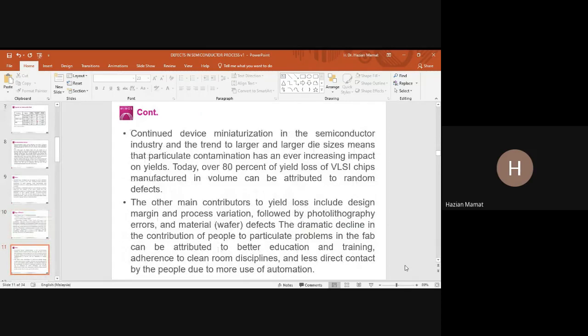Okay. Continued device miniaturization in the semiconductor industry and the trend toward larger and larger die sizes mean that particulate contamination has an ever-increasing impact on the yield. If we go to the trend of the size of the wafer, we have 100 mm to 150, from 150 to 200 mm, from 200 mm to 300, and now the latest one is 450 mm, which was supposed to be introduced in 2018, but it has not happened because of cost. The cost to build a foundry is very high.